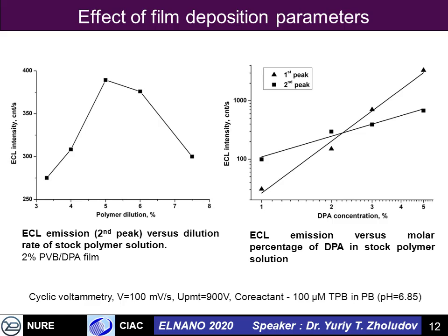On the left picture you can see the dependence of ECL intensity for such films versus the dilution level of the polymer. By changing the dilution ratio with the solvent during the deposition process, the thickness of the films changes. Here it is given as a percentage of the stock solution dilution, and it is clearly seen that there is a distinct maximum of ECL emission. For less diluted films, the density of the film is too high, so it is not really permeable for electrochemical processes. When the film is too diluted, probably there is not enough active species, not enough fluorophore to participate in the ECL reaction, so the ECL decreases. So there is a clear optimum, and the parameters of this optimum were used for ECL studies in the future.